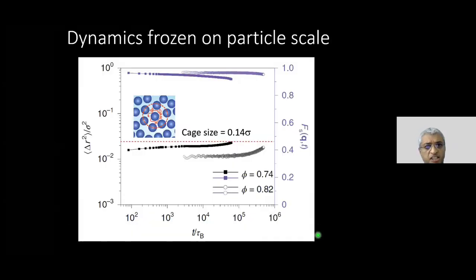Okay, so first, to convince you that I do have a glassy state, I am plotting for you the mean square displacement scaled by the particle diameter, and I'm also plotting the intermediate scattering function, shown here. And as you will see, both of them are completely flat. This dashed line here is basically 0.14 times sigma, which is the cage size, the volume available for a particle to rattle. And you will see that over 10^5 tau_b or 10^6 tau_b, I never see particles moving at all. Forget their particle diameter, they don't even move 1/10 of their particle diameter.